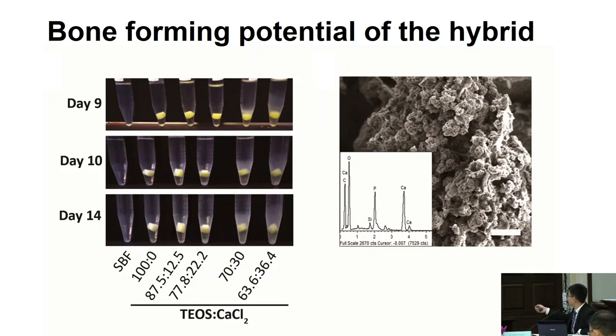And when we collected the crystal, and also the coagulation on the surface of the scaffold, we proved that there is a concentration of calcium and phosphate in a very similar ratio to hydroxyapatite. So we concluded that our hybrid scaffold can form hydroxyapatite, the same as in the bone.